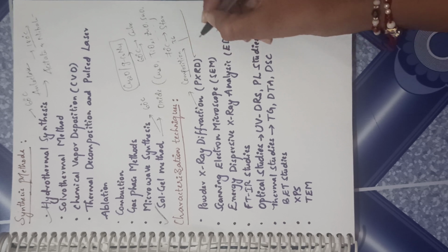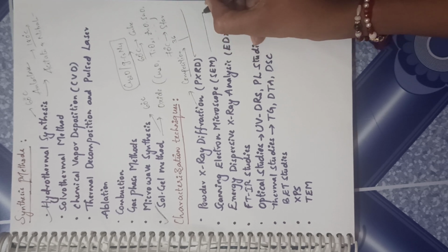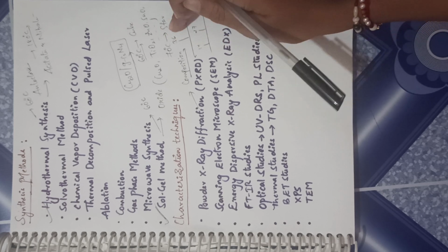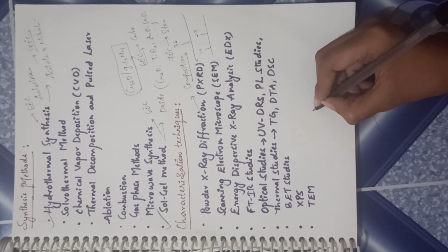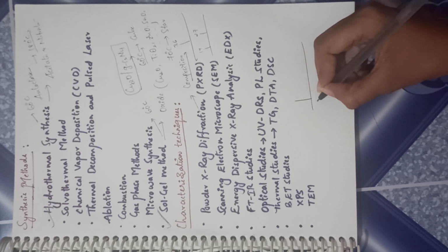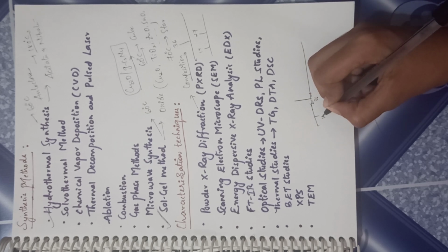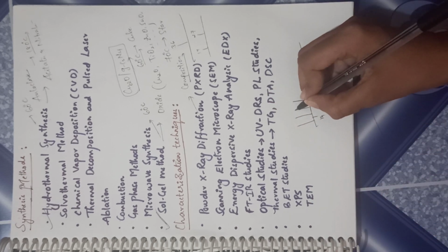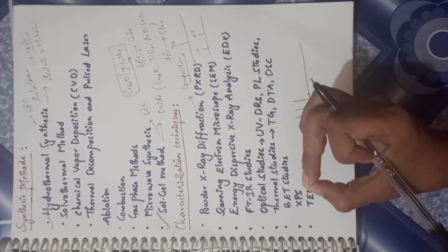Let's say Cu2O has some peak around 36 and graphitic carbon nitride individually it has peak around 14 and 27. Now these are individual XRDs of Cu2O and graphitic carbon nitride. Now what should happen in the composite is that the peak should be somewhere above or below the 36 value, and the same with graphitic carbon nitride. Let's say 14 was the actual peak, your peak should be either above or below 14. The same with even 27. It means there has to be some shift in the peak position if a composite is formed.